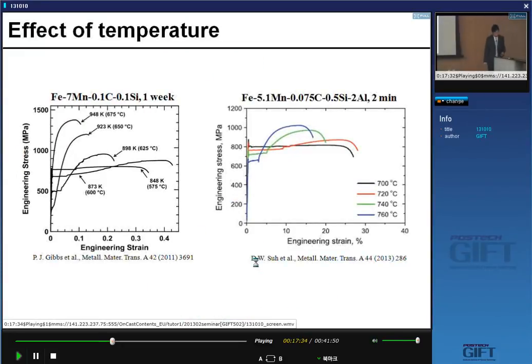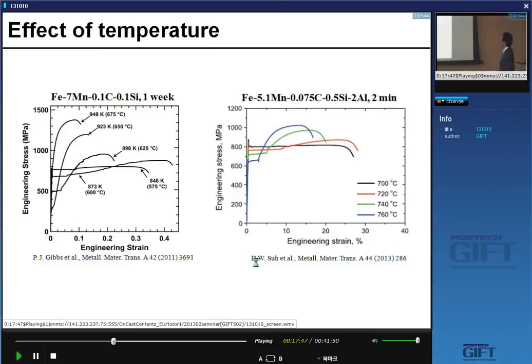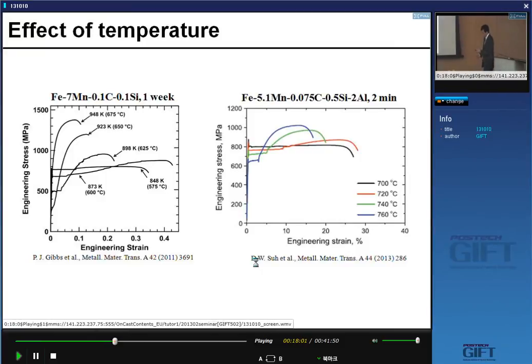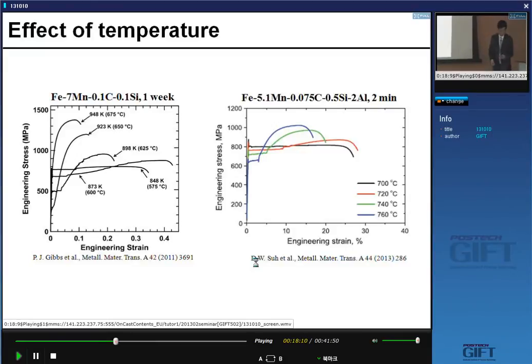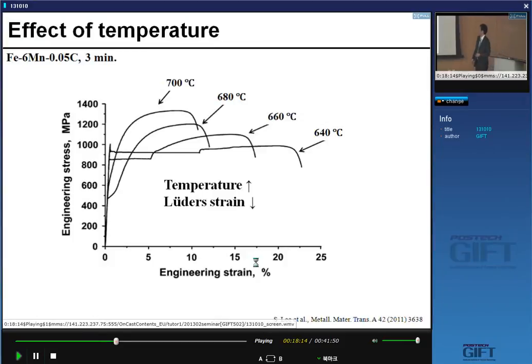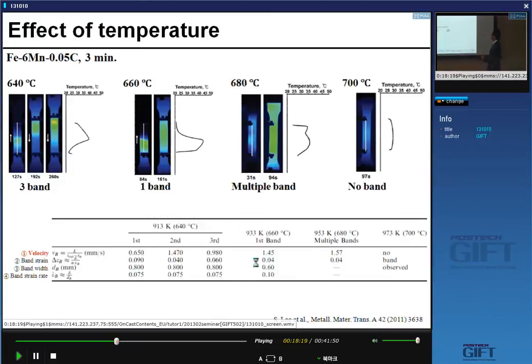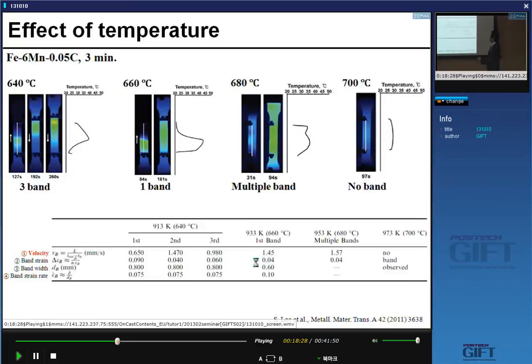Next is the annealing temperature effect on tensile properties. The flow curve changes hugely depending on the annealing temperature. At intermediate temperature — when retained austenite volume fraction is large — we have good ductility and reasonable tensile strength. Another interesting observation is Lüders strain, which represents local deformation. When the annealing temperature is high, we have small Lüders strain. With increasing annealing temperature, we can see deformation band propagation through the gauge length, and deformation band behavior depends on the annealing temperature.